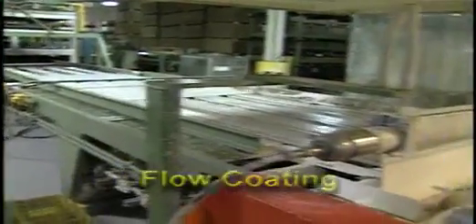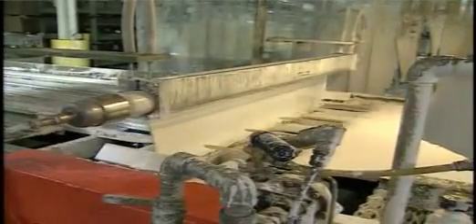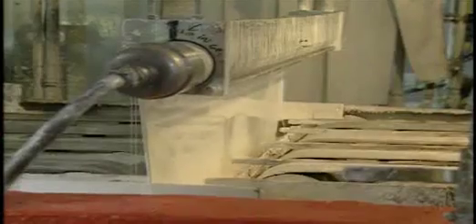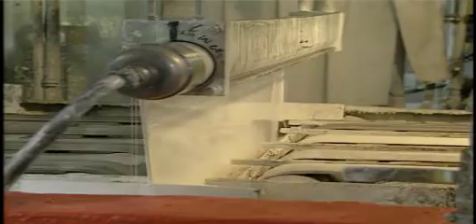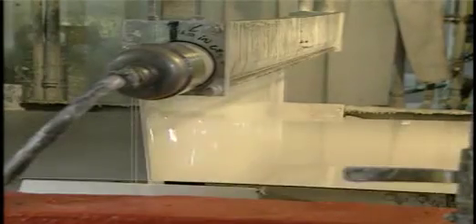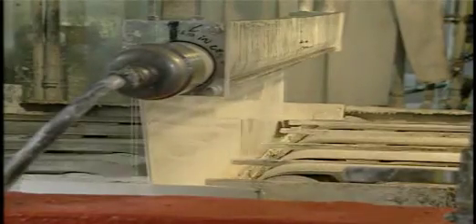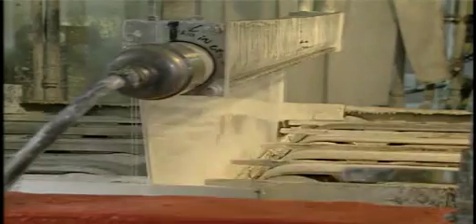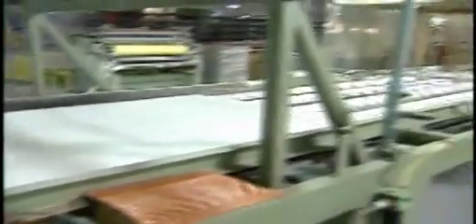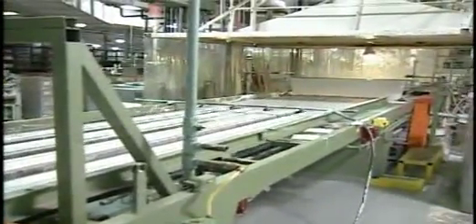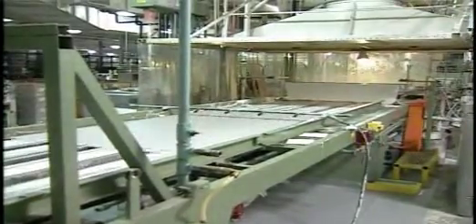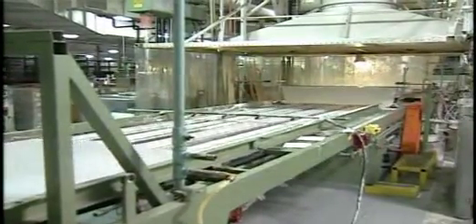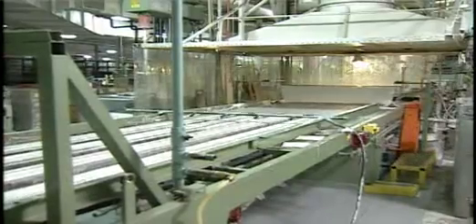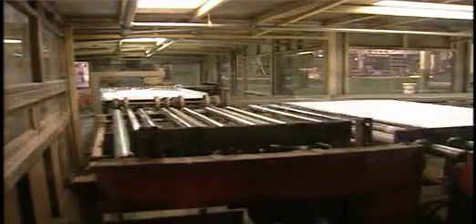In flow coating, the coating is pumped through overhead nozzles and allowed to flow over the parts to be coated. In some cases, warm air jets may be directed toward the parts to improve coating uniformity. The excess coating drips off the parts and is collected and returned to the main tank for reuse. Fresh coating and solvent are added to make up for usage and evaporation. Transfer efficiency for flow coating is approximately 85%.